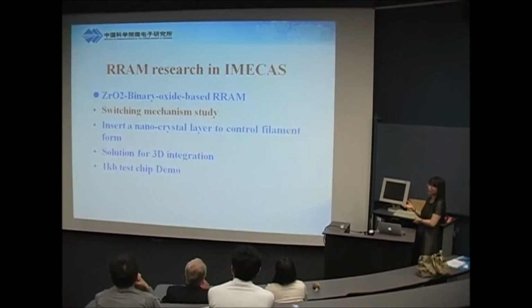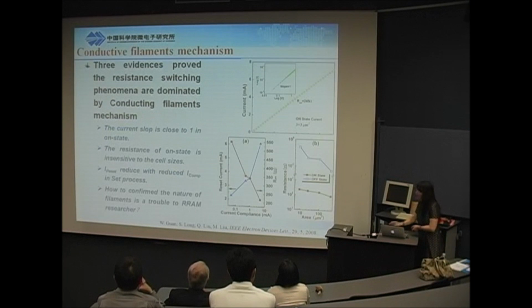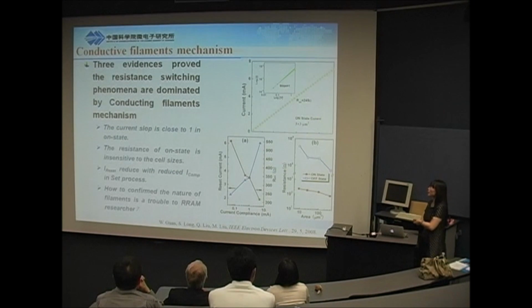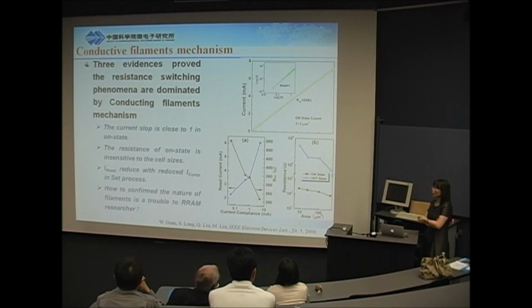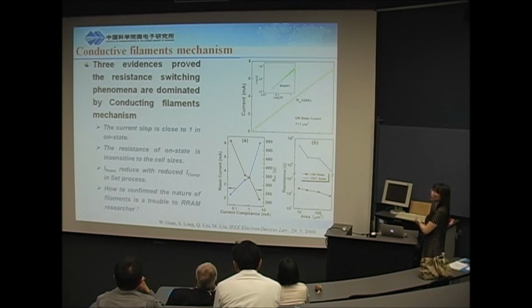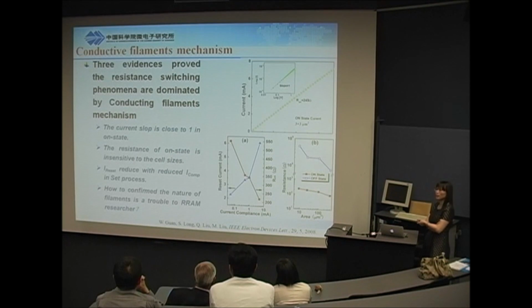So for the second part, after we fabricate the device, we would like to understand the switching mechanism. First we use the electrical measurement, and from this measurement we can deduce some of the mechanism. First, the current slope is close to 1 in the on state, which means the on state behaves like a metal. Another point is that the resistance of the on state has no relationship with the cell size. Different cell sizes give the same resistance. That is easy to explain if in the on state a metallic conductive filament is formed. The resistance depends just on this filament, so the cell size has little influence.